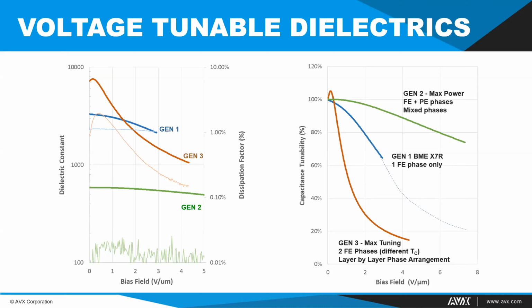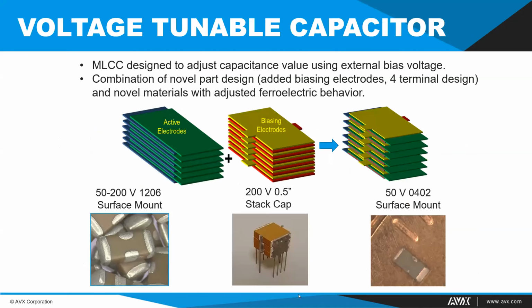Based on these types of materials, we also conceived some devices that took advantage of this design. You can see that by combining a set of active electrodes, which look like the standard electrodes that would appear in a device, with a set of biasing electrodes, and adding a set of terminals to the outside of the device, we were able to create multi-terminal devices that allow you to separate the function of the bias voltage from the signal, which would probably be applied on the transverse or along the length direction of the device. So this allows someone to apply a biasing voltage without making a complex signal which has a bias applied to it, which must be separated out later.